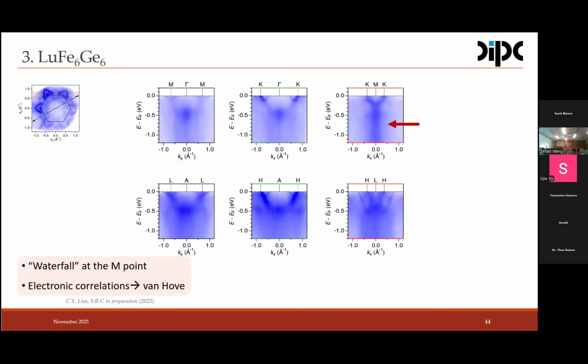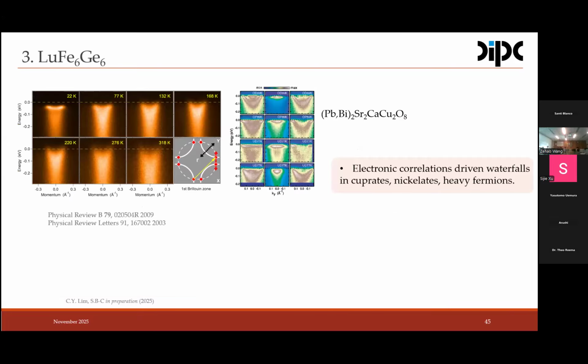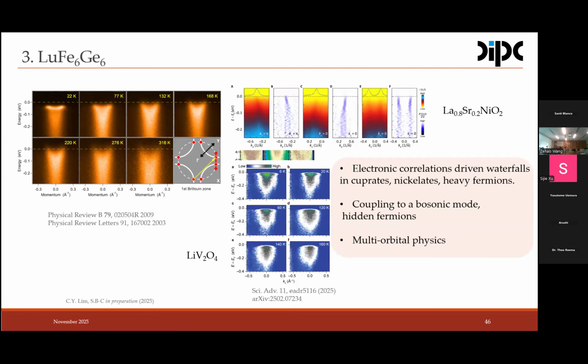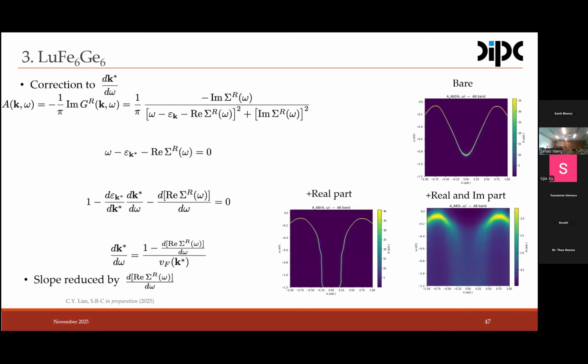And this waterfall of intensity is actually very well reported in strongly correlated materials, like in cuprates, and more recently nickelates, and I think this is the heavy fermion compound lithium vanadium 2 oxide, a further recent arXiv paper on Kagome. So this waterfall of intensity is a hallmark of strong correlations in the energy spectrum. I mean, there is still a strong controversy about that. It might be driven by the coupling to bosonic modes, hidden fermions, multi-orbital physics, and so on and so forth. We are not sure where this comes from, but we made a first preliminary analysis. Actually, we have a second analysis of this, which I got yesterday or 2 days ago, which is more advanced.